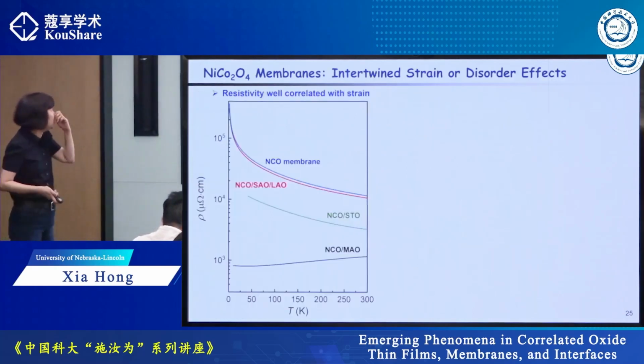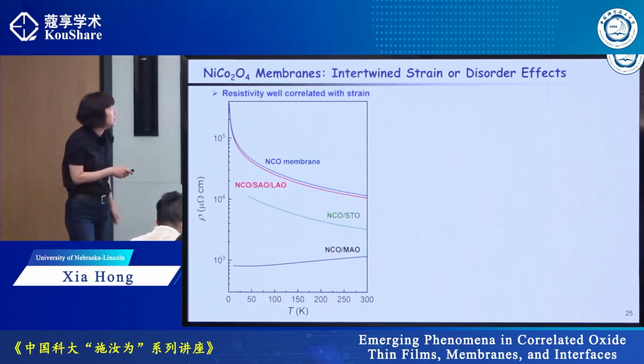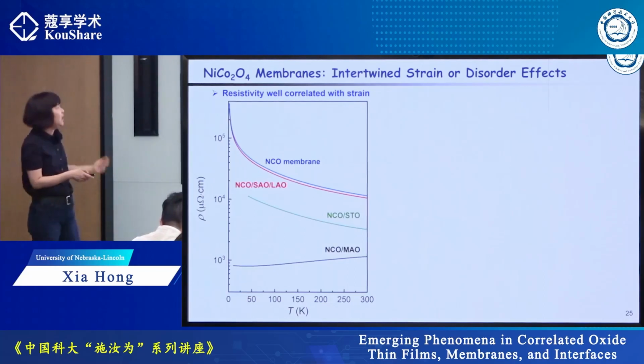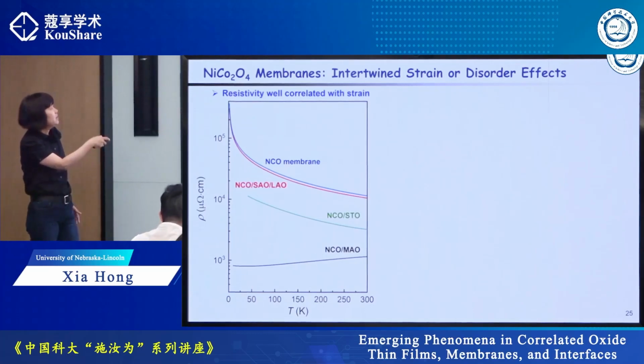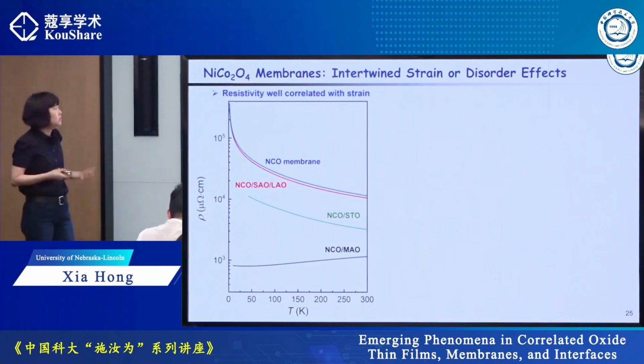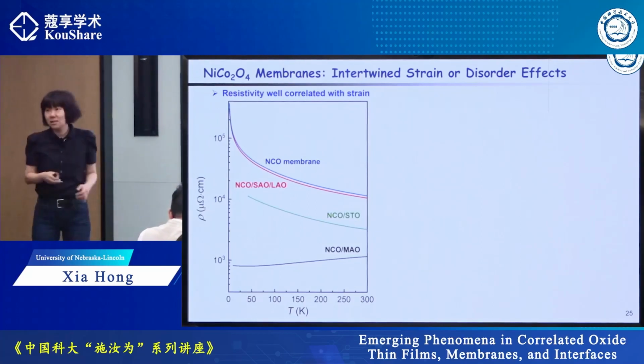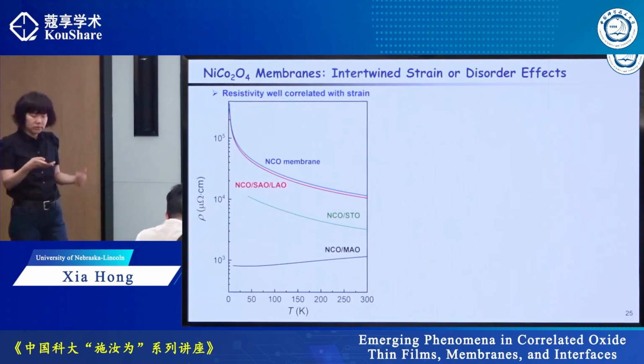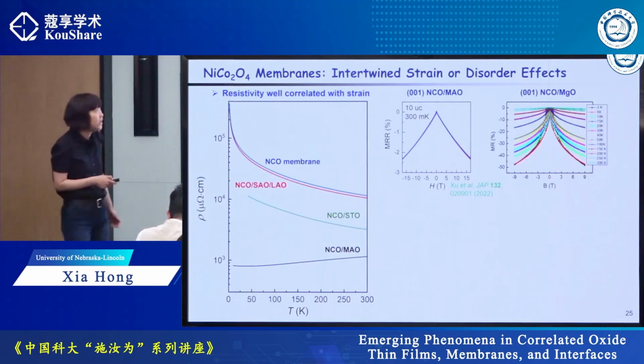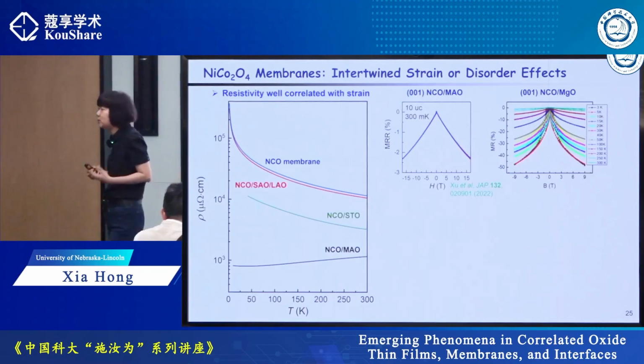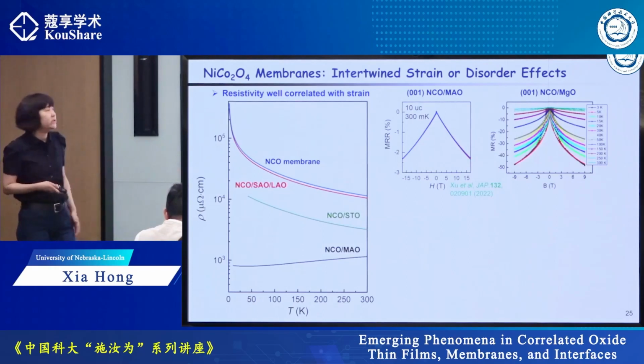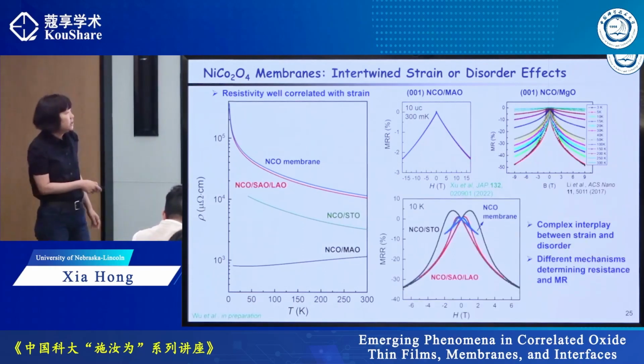And first we study the temperature dependence. We find that the sample is no longer metallic. It's actually more insulating compared to its epitaxial counterpart. This is before water etching, this is after water etching, and resistivity does not change a lot. So this says that probably the growth introduced more defects. And I mentioned that you can use magnetoresistance to check the crystallinity of the film. So we compare the magnetoresistance of different systems.